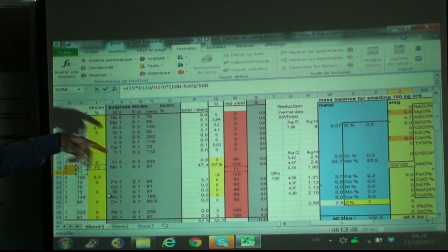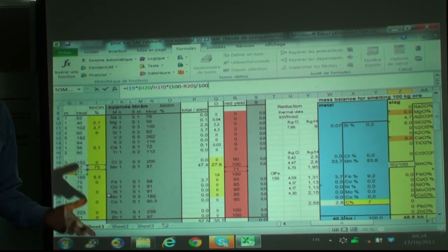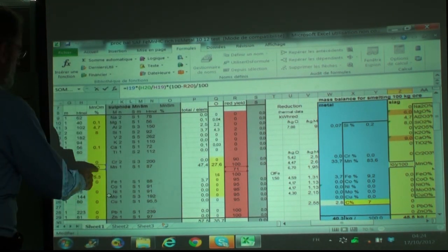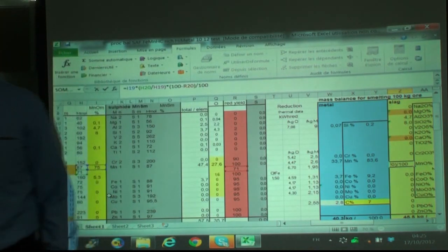So this is just saying that the kilos of MnO in the slag are the 75 kilo corrected by the molar mass of MnO versus MnO2, and from this corrected value you take 29%, because 71% you reduce, it goes in the metal, and 100 less 71%, 29%, is going to the slag. Okay?